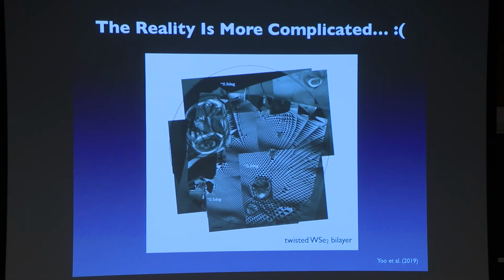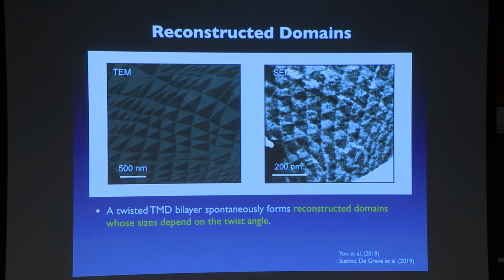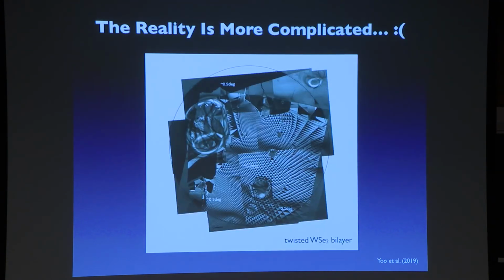And this one is actually something that I probably should not get into. Whenever somebody shows you these nice-looking pictures, be suspicious, very suspicious, because the actual picture looks like this, and we are picking out this region and then showing it to you. So one of the things that we should learn how to do and how to improve at the moment is that although by twisting those two bilayers, we can generate lots of interesting patterns, as of now, we do not know how to control the disorder that well. So actual large-scale samples look like this, out of which we are concentrating on particular regions. So one of the things that we are now trying to do is to make those textures as perfect as possible so that we can generate these patterns in wide regions, at the wafer scale, so that we can actually start to use them to do some interesting things.